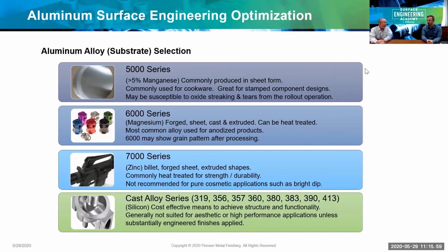Unfortunately, though, some of the castings have a lot of other metals in them. It's not just a singular alloying element. Porosity is more common. The two main types of castings are to pour the casting or to do high-speed injection die-cast type materials. Right, and with casting, Steve, you typically get a lower thickness potential, right? So corrosion resistance, wear resistance reduced. There's ways to overcome that.